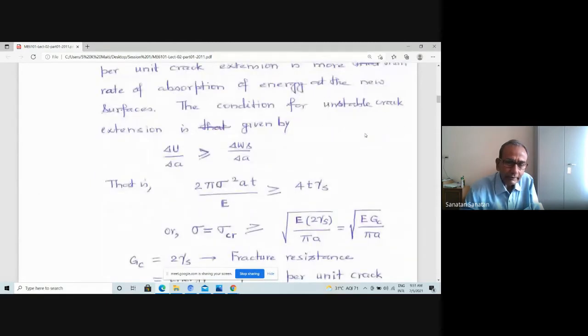And therefore, with all the calculations, if you say delta U is the strain energy change per unit crack extension, and the energy required per unit crack extension is delta Ws by delta A, then this is the condition of unstable crack propagation. If your availability of energy is more than the required, it is going to lead to unstable crack propagation. And these calculations finally gave the critical stress capacity of a material, of the type sigma equal to sigma CR, which is nothing but square root of 2E gamma S divided by pi A. So this is the form of the new expression.